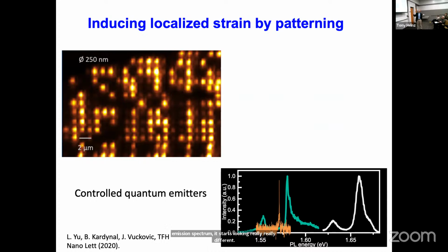So this is 250 nanometers. This is more like a 20 nanometer hole. And then we see these very sharply defined features. So there actually are several reasons the line gets sharper. Some of them are sort of experimental in character, that you always have some inhomogeneous broadening. If you make the emission area very small and you look at only one of them, you basically eliminate inhomogeneous broadening.